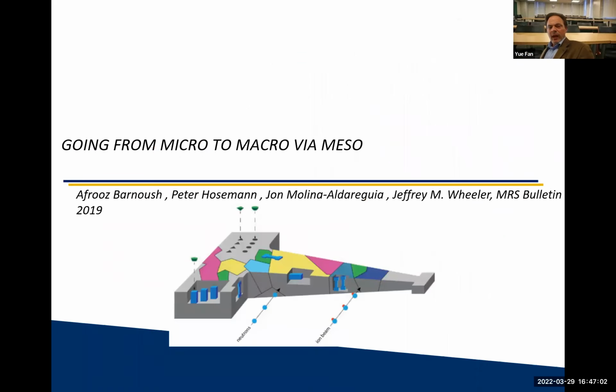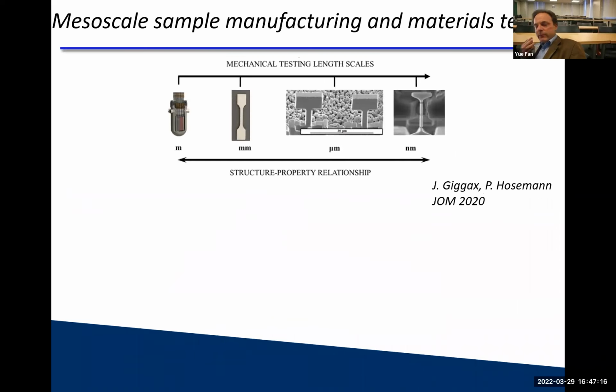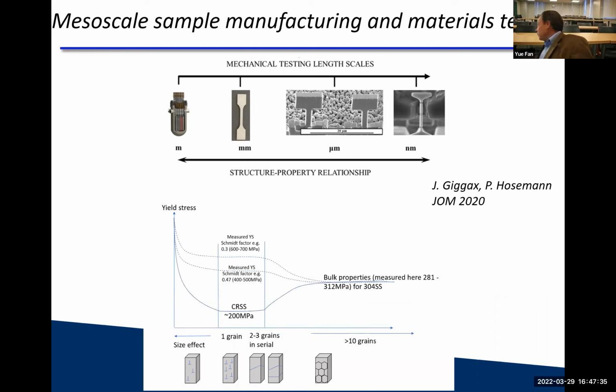All right. Of course, we do all this at a micro scale. Now let's do this at a slightly larger length scale, because at the end of the day, we want to get bulk properties for our reactor. And one challenge we have is people have been doing tensile testing using focused ion beam machining for the last 10, 15 some years. And our reactor, however, is in the millimeter length. And what's missing is sort of this stuff in between, the 100-ish, tens of microns length scale. Because the question is, how does your nanomechanical performance relate to your macro performance?